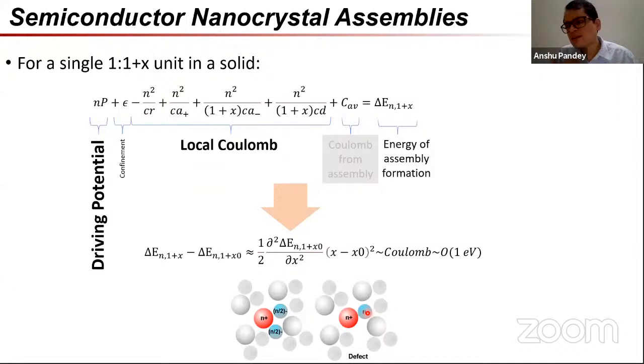This incurs a fairly severe penalty, which effectively is a Coulomb penalty. This Coulomb penalty, if we calculate with the numbers that we have, comes out to be of the order of an electron volt. And suddenly that's an energy scale where it becomes possible for us to show that the system has the ability to put a stiff penalty on stoichiometric defects. So it always tries to have one stoichiometry without taking recourse to either a quantum mechanical shell filling effect or to having any other form of short range order based scheme. So this is a little odd how this thing comes about. That's how it works over here.